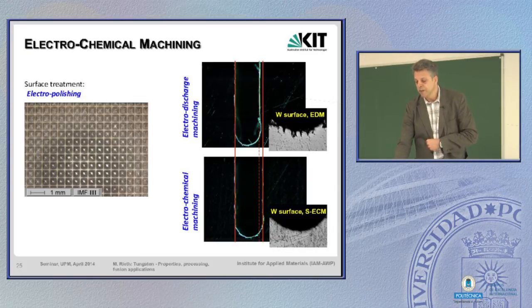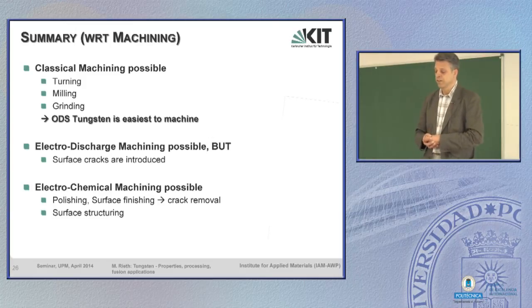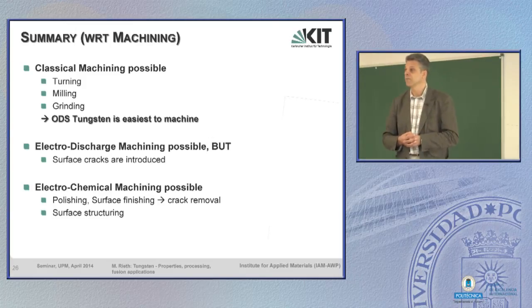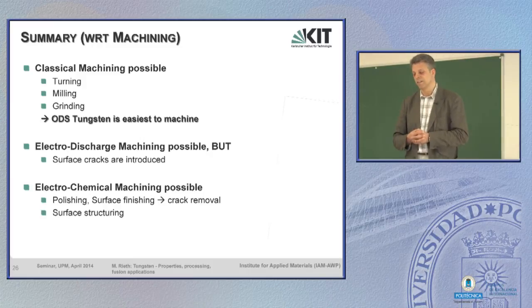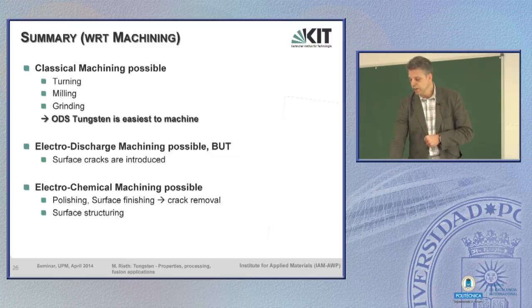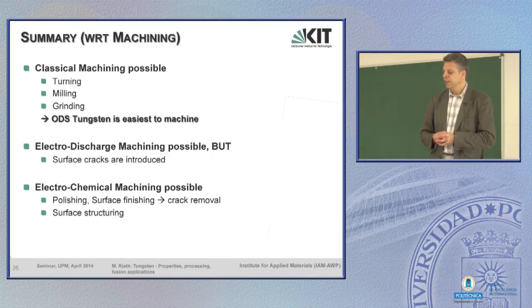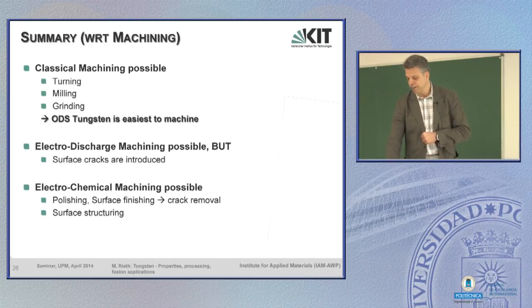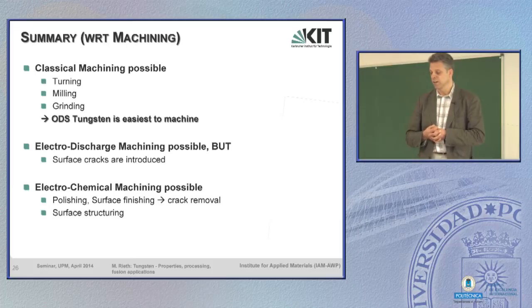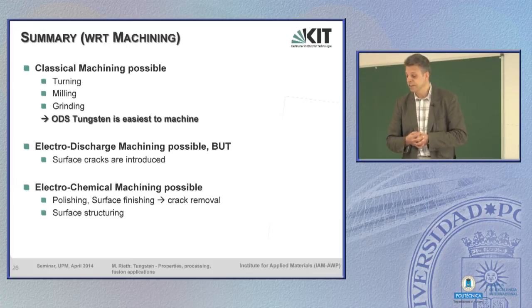Also here, quick summary. Classical machining is possible, turning, milling, grinding, etc. That's, let's say, not a big problem. The ODS tungsten is easiest to machine. Electro-discharge machining is possible, but surface cracks are induced and we don't like to have them. Electrochemical machining is also possible. It's preferable to electro-discharge machining because you can polish the surface, finish the surface, and also use it for crack removal or surface structuring.